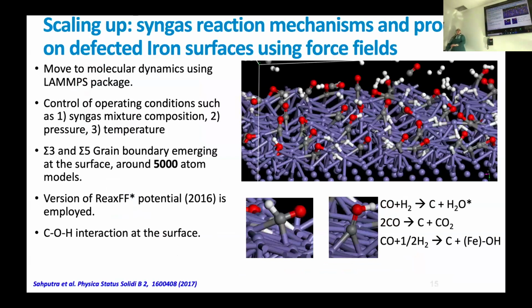Taking that forward, we have been able to run molecular dynamics simulations using LAMMPS. And we had the chance also to control the operating conditions. So in this case, we could explicitly take into consideration the gas mixture, which is carbon monoxide, water, hydrogen, and also CO2 in this entire simulation. Using this technique, we could also simulate the impact of the sigma 3 and sigma 5 grain boundaries that are emerging at the surface, for a sample of 5,000 atom model. And we have been able to characterize and fully understand the carbon, oxygen, and hydrogen interaction at the surface.